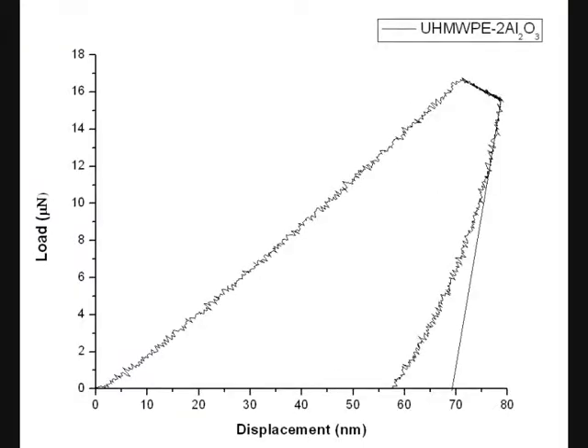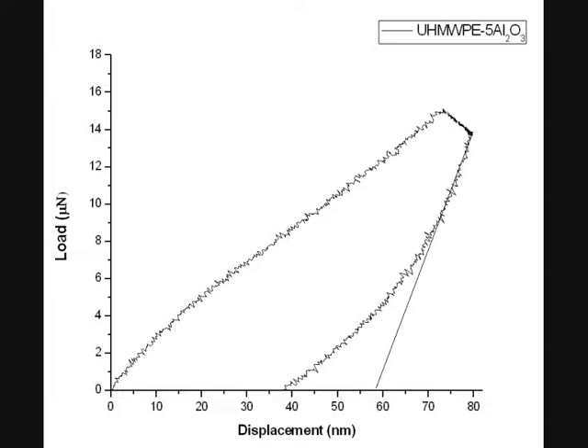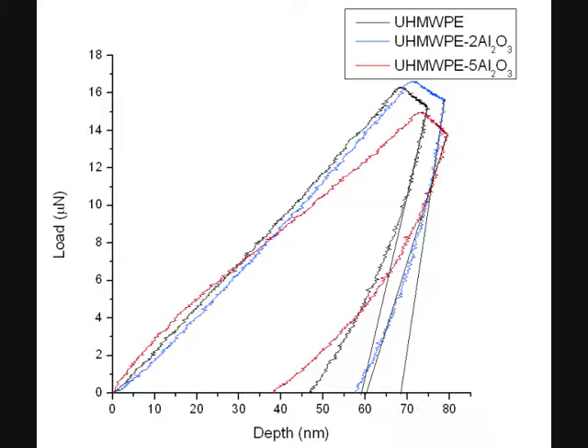This is the load displacement curve for ultra high molecular weight polyethylene with 2% aluminium oxide, and here we can see that the maximum load is still in the range of 16 micronewtons, but the maximum displacement is around 70 nanometers. And this is the curve for ultra high molecular weight polyethylene with 5% aluminium oxide composite. In this slide, a comparison between all three specimens has been presented.